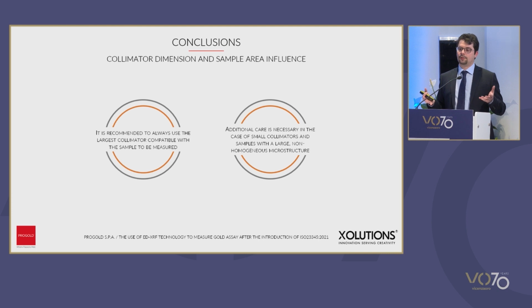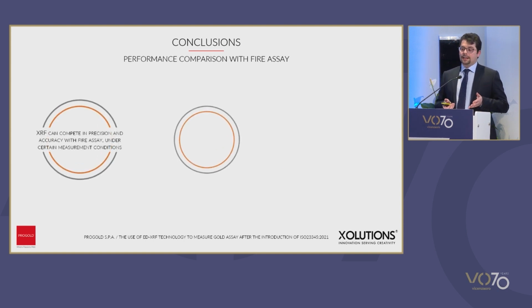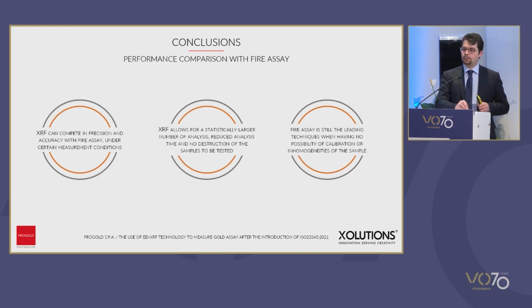And then we have seen that we have to use the biggest possible collimator in order to maximize the statistics about the atoms measured, and then we have to look at the homogeneity of the microstructure. And then we have seen that the X-ray analysis can, in some alloys and under some conditions, be comparable in terms of performance with the fire assay. Well, this doesn't mean that we ask you to move from fire assay to X-rays, because both these techniques have their weak points and their strong points. But the X-ray technique makes very fast analysis and does not destroy the samples.